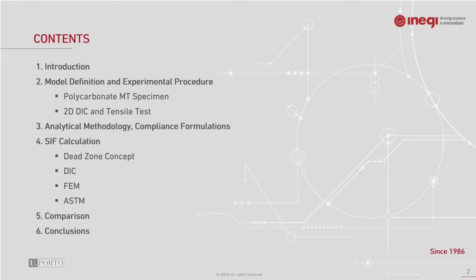So my talk includes introduction, model definition, and the experimental procedure, actually focusing on the polycarbonate middle tension specimen, in which 2D digital image correlation and the tensile test have been included. And basically the next stage is related to the analytical methodology based on the compliance formulations, and as a result SIF calculation is going to be presented based on the stress dead zone concept, digital image correlation, numerically by the finite element method, and a reference solution is going to be given by the ASTM standard, and afterwards the comparison and the conclusion of my work.